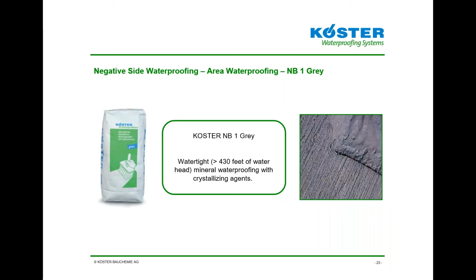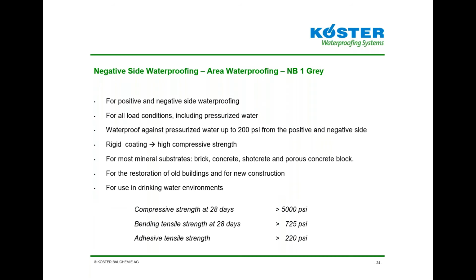The NB1, like I said, is the much more popular product, a capillary crystalline cementitious coating. That's watertight with upwards of 430 feet of head pressure. It's mineral waterproofing with crystallizing agents. This is what we call our capillary crystalline coating, where these crystals form in the capillaries of the concrete and block moisture intrusion that way. NB1 gray can be used for both positive side and negative side waterproofing, primarily against moisture ingress, including pressurized water. Waterproof against pressurized water up to 200 psi from both the positive and negative side.